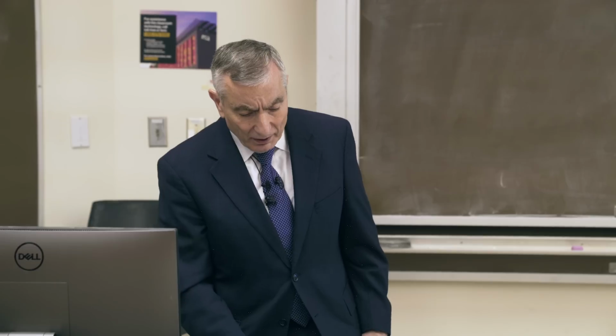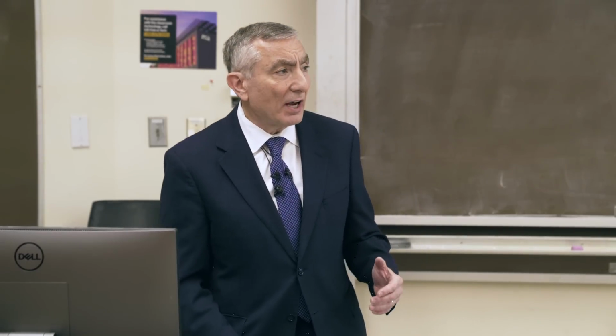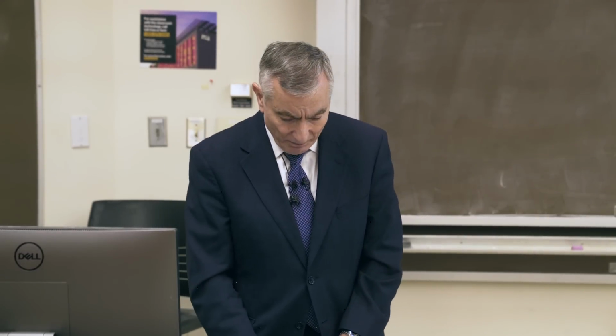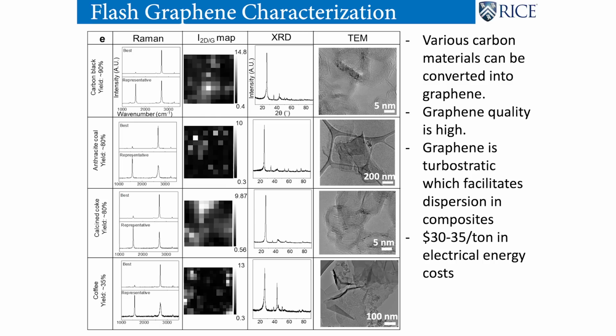And if you want to see the best spectrum that's ever been published on graphene, here it is. This is the G band. This is the 2D band. It's a 17-to-1 difference in height between the 2D and the G band. That's not the D band, not the disordered band, but the G band, the graphitic band, this little thing here. The 2D band is very large here. So it's tremendously clean graphene, and this is because you have a turbostratically stacked graphene.